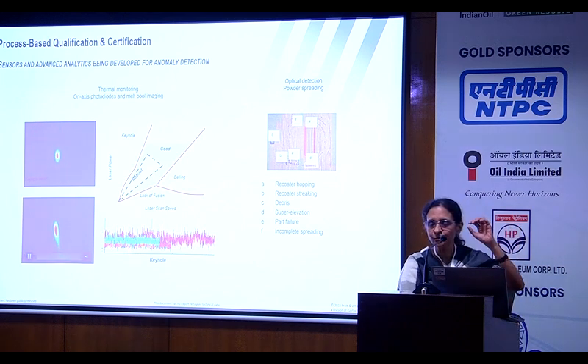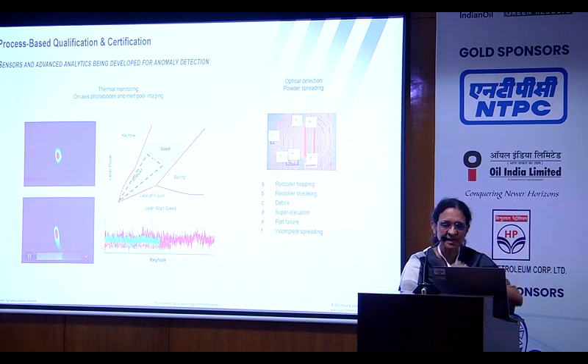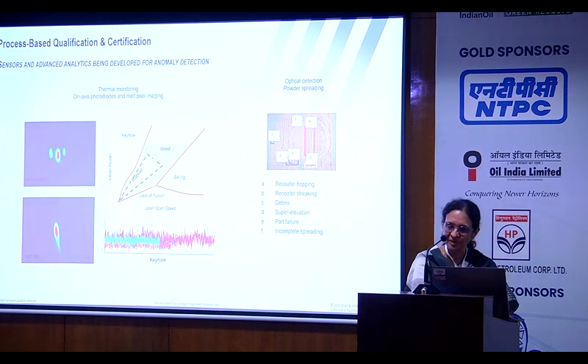So the top tells you there is a spatter in that particular layer, and there is a process map that we have done in the lab with simple sample coupons, and we relate. And the bottom, you can see there is no problem at all. It's very uniform. And then we develop a process map for this particular geometry, for this particular alloy chemistry, because it's very dependent on the chemistry of the superalloy as well. And then we are also working a lot on this particular aspect towards industrialization.